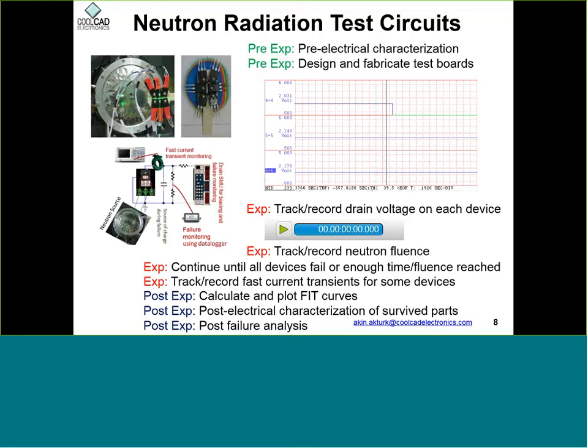Since there are 6 devices in this case, if one fails, you don't interrupt the experiment, and you wait until either an appreciable number of devices fail or a large enough fluence is reached. And once you have statistics about which devices failed due to X amount of neutrons, then you can calculate the failure rate curve or failure cross sections, and you can use them to calculate failure in time curves, which I'll explain a bit later.